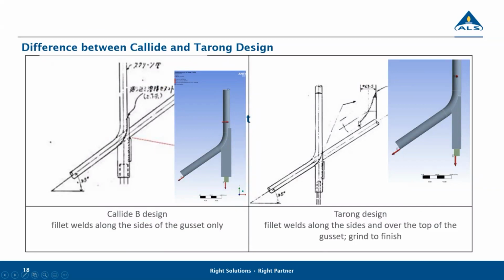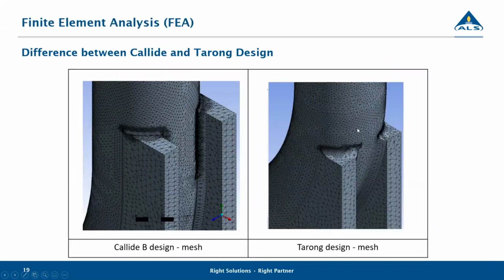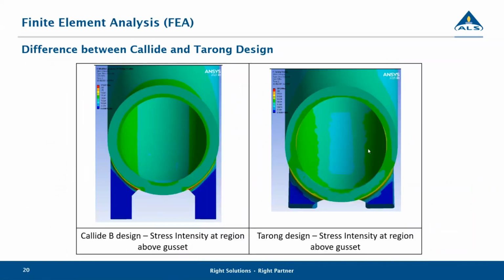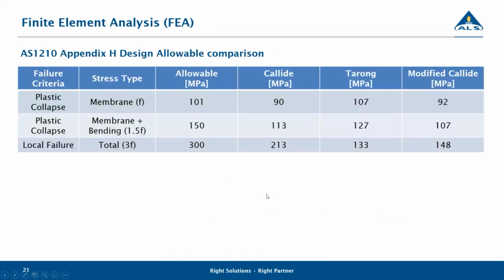And Tarong has not experienced a failure like this. So that's typically what the 2 different designs look like. So that's a very sharp, abrupt end, where the Tarong one is more blended in. If you look at the stress results, we got the same, where you saw that fatigue crack develop and moving in. We got that same response just above the toe above the bracket. So not on the bracket, but just above it, and similarly for the other side as well. So you can see the difference in thickness, as well as the difference in stress response.